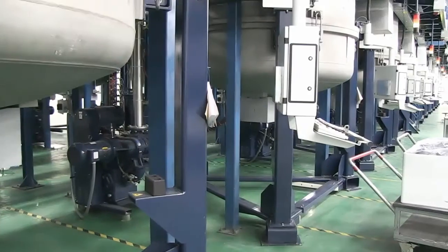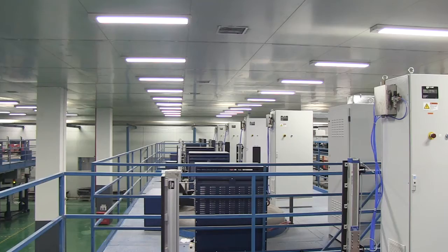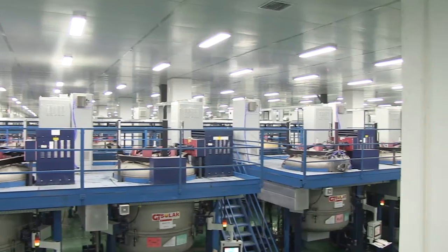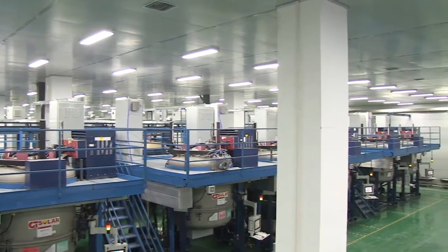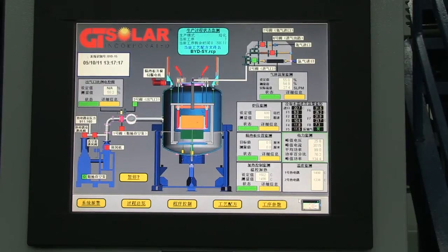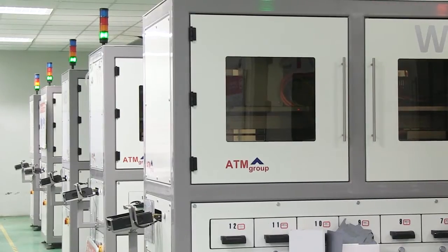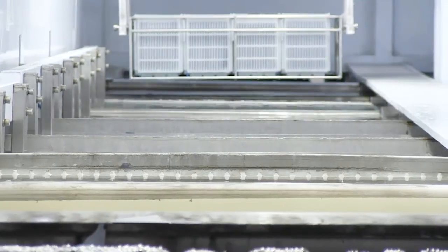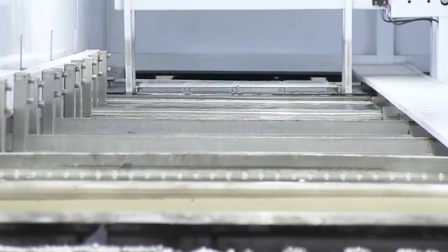After a series of production processes including squaring, band saw, chamfering grinding machine, surface grinding machine, wire saw, and cleaning process, BYD can make silicon wafers with a thickness of only 180 microns. After rapid improvement in the wafer producing process, BYD wafer has reached high and stable quality in the PV industry.